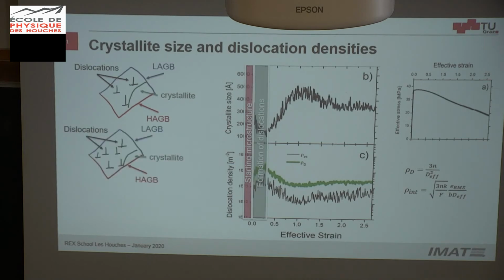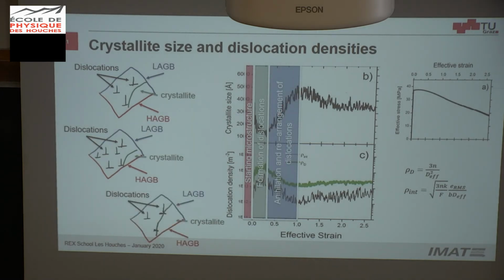When we start the deformation, dislocation densities start to increase, so interior dislocations within the cells increase, the crystallite size starts to decrease, and this is what we see here, this drop, together with the increment in the dislocation density. And this is for a very small effective strain. If you see here, we deform up to almost 3. But then when recovery starts, these dislocations are arranged into low angle grain boundaries, and interior dislocations start to annihilate, so the crystallite size increases again and the dislocation density decreases.